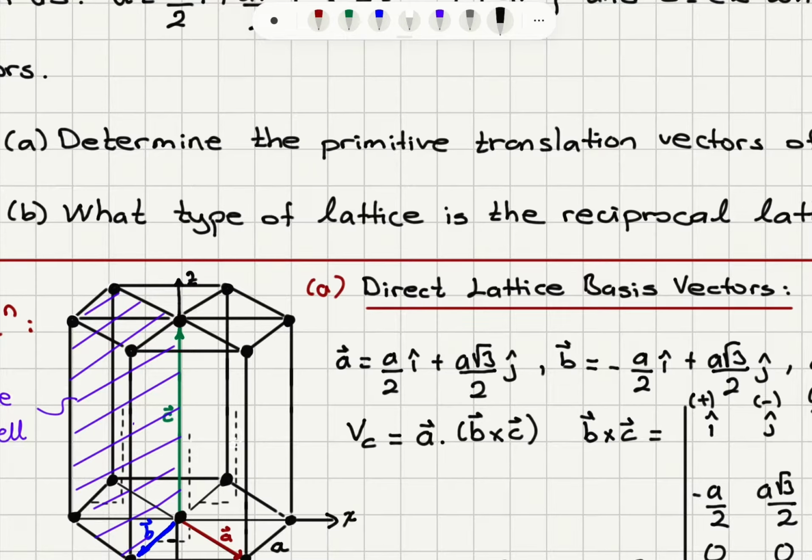So there's a factor of 1/2, and because of the 120-degree angle, for example, here I would have a 120-degree angle, so it's going to be shared, because the total is 360 degrees. 1/3 of this one is inside this unit cell, and 1/2 is on top and 1/2 is at the bottom. So I will have 1/6 of this lattice point included in this unit cell.